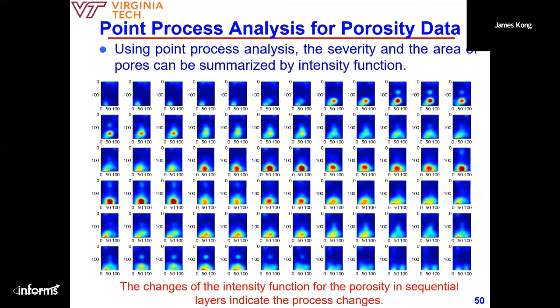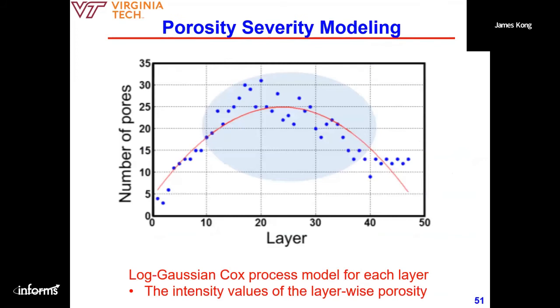So this piece of work was published in IISE Transactions. And then for each layer, if we are able to evaluate the average intensity, you see this red color means high intensity or high risk of the porosity, right? The blue color means low risk of porosity. Then for each layer, we estimate the average intensity. Then we plot the intensities along the different layers. We can see at the beginning, the porosity was not that severe. At the middle, it's pretty bad, pretty high level of porosity. At the end, the layers also decrease, right? They have quite a strong layer by layer spatial correlation there.